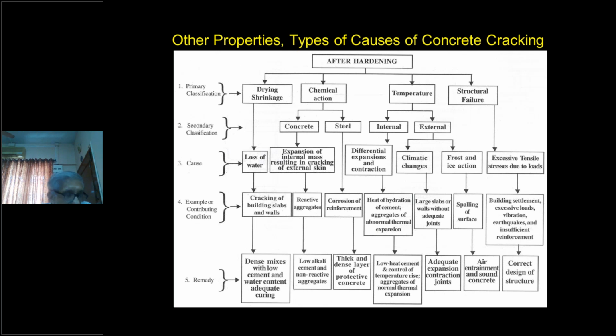So concrete has a lot of porosity. Some of them you can't see because it is a microscopic porosity, and some of them you can even see. Cracking of building slabs and walls do occur. The remedy is dense mixes with low cement and low water content, but most important, adequate curing. This is extremely important. I will show you some of the Mumbai roads which have cracked because of maybe poor curing and also not planning the construction properly.